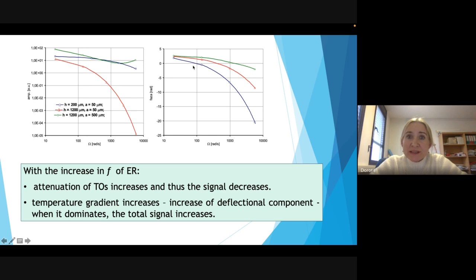Here we have the amplitude and phase of the signal for different radii of the probe beam. So what we see in general is that the signal decreases very strongly with the increase in the value of modulation frequency. Why is it like that? This is the result of strong attenuation: with the increase of modulation frequency, the attenuation of temperature oscillation strongly increases, thus the signal decreases. But with the increase of modulation frequency, the temperature gradients also increase.